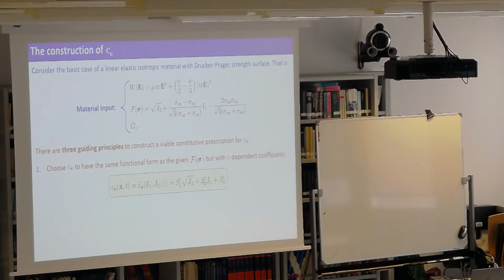The driving force that you choose is of the same functional form as the strength surface, except that you have coefficients that are epsilon dependent. So you give me Drucker-Prager, my driving force is Drucker-Prager, but I have coefficients. And these coefficients have to do something when epsilon goes to 0. Remember that epsilon is a regularization parameter. We want to pass to the limit. We cannot, but ideally we want to pass to the limit, right?